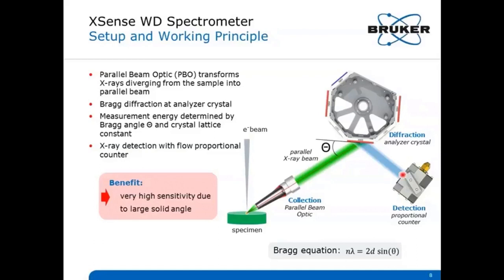According to the Bragg equation, the energy, or the wavelength lambda, of these photons is a function of the adjustable Bragg angle theta, which is the incidence angle of the beam relative to the crystal surface. Theta is given here. This is the incidence angle between the crystal and the X-ray beam. And the second parameter is the lattice constant D of the analyzing crystal.